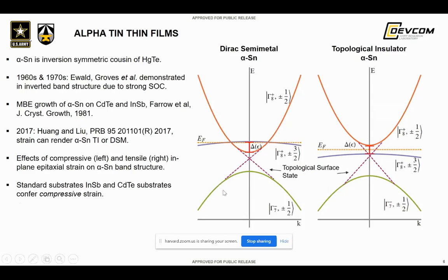This slide just shows the typical band structure of the material as you go from the Dirac semi-metal to a topological insulator. In one case, you can see that Dirac cones are formed, and you can see a Dirac crossing at a Dirac point. This is usually the case where you have a Dirac semi-metal, where the band gap is inverted so that the valence band of the gamma 8 is actually higher than the conduction band, and you get this Dirac phase. And when it's gapped, as shown here by strain, you can get a topological 3D insulator.